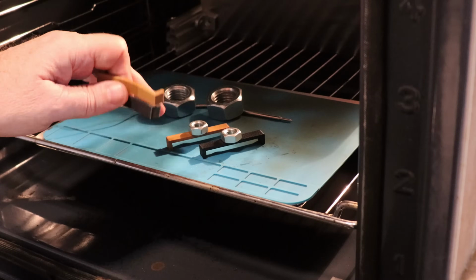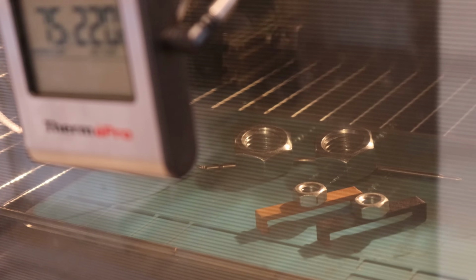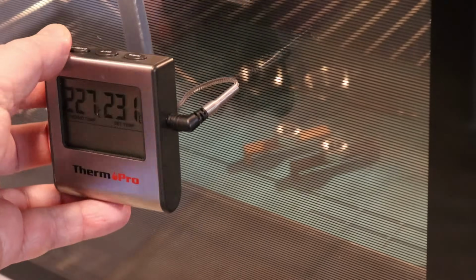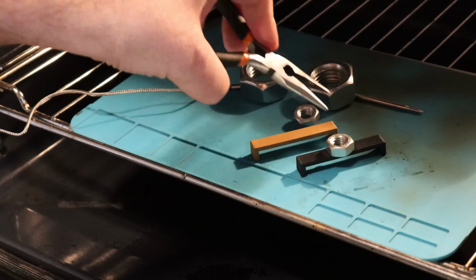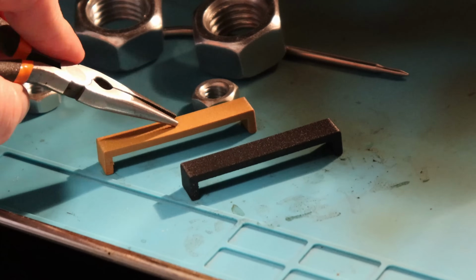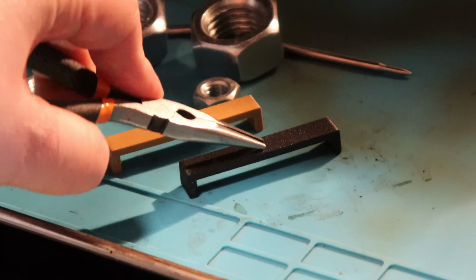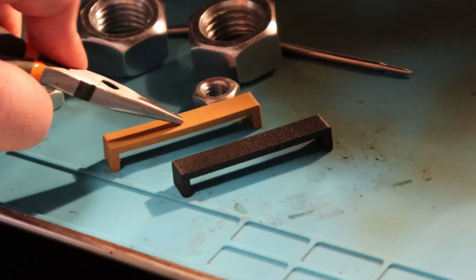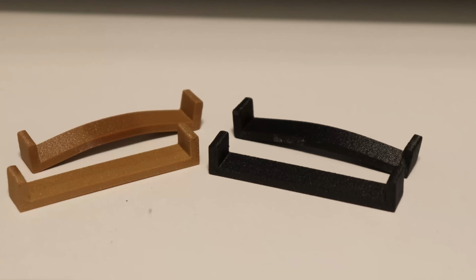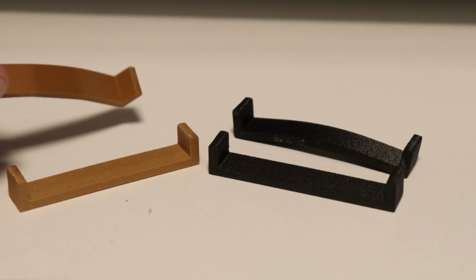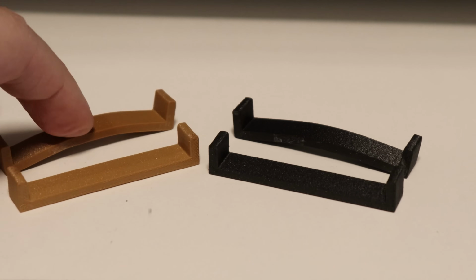And now the second attempt, so these are annealed. And again the temperature test in the oven, this is an extremely sped up video. And you will see there is no deformation on these test objects. I stopped the experiment at 227 degrees Celsius. And I wanted to see how hard these materials are, and they are still completely hard and usable. Even now there is no visual deformation on annealed test objects, and it's interesting to notice that we have this color change because of the different temperatures.